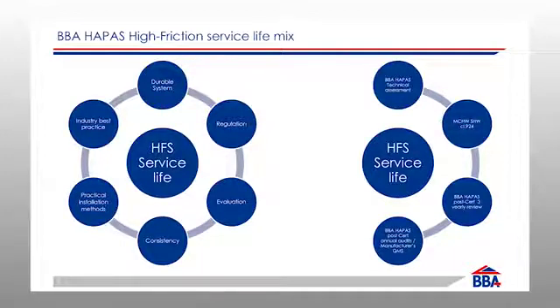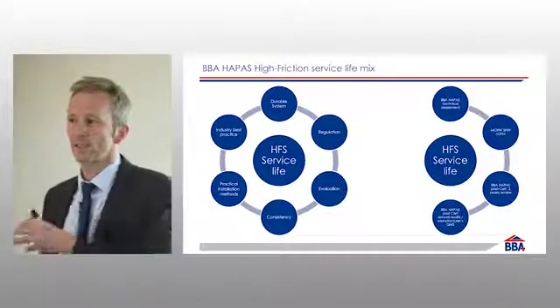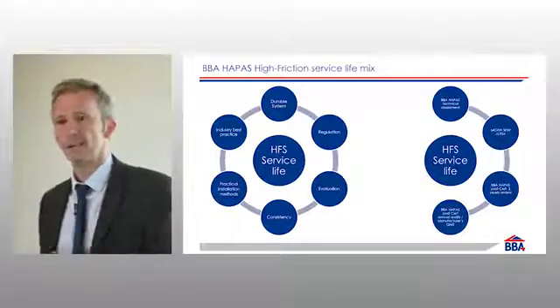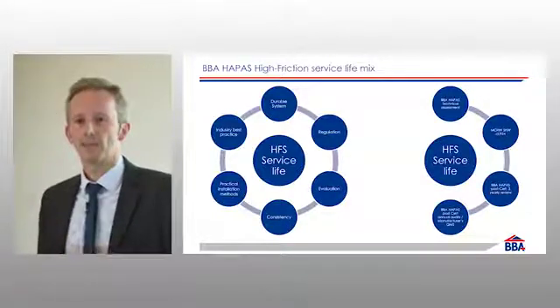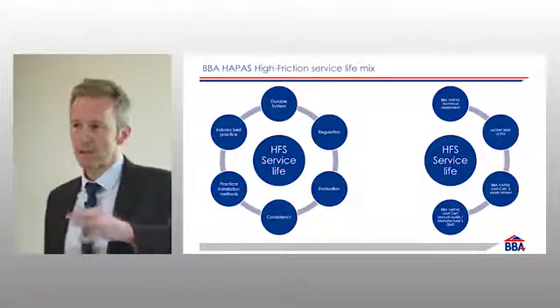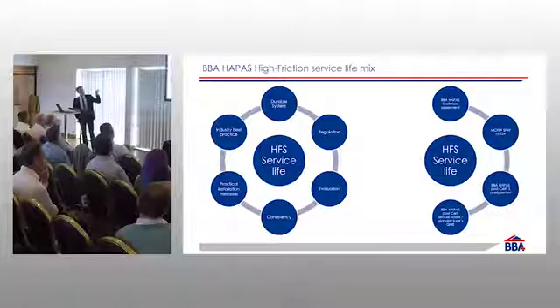There's laboratory tests where we take samples and put them on slabs, and we measure skid resistance using the pendulum. We also do a 2-year trial, which measures the performance at 6 monthly intervals over 2 years. Performance being skid resistance, texture depth, and its visual condition, and wear characteristics as well. So it's lab and it's on-site, it's in situ. So the technical assessment does that.